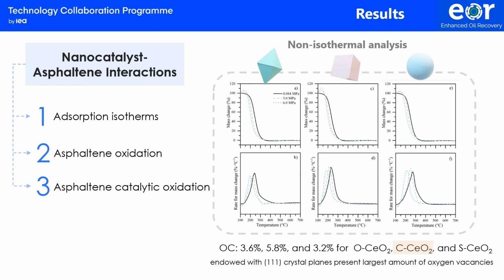Raman, transmission electron microscopy, and X-ray photoelectron spectroscopy analysis demonstrated that the cubic nanocatalysts, endowed by the 111 crystal planes, present the largest amount of oxygen vacancies, which promote an effective oxygen diffusion from the gas phase or catalyst bulk phase to the surface of the asphaltenes. Therefore, this is the catalyst with more active oxygen for enhancing the reactivity of the asphaltenes.